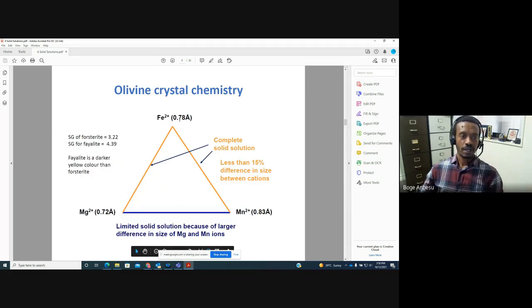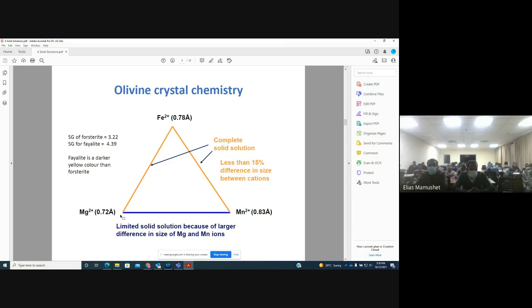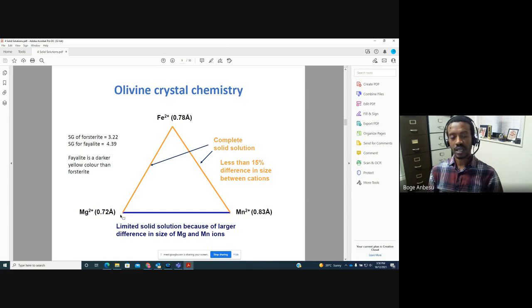So in olivine, if you look at iron 2+, its size is about 0.78 angstroms, and magnesium has 0.72 angstroms. So because of that comparable size between the two, if the size difference is less than 15%, then you could have one replacing the other. But if the size is too big, for example, between magnesium and manganese here, because manganese is bigger, they don't actually make a solid solution between the two. But iron and manganese can do the same, because the difference in size between iron and manganese is less than 15%. So again, these are some of the requirements.